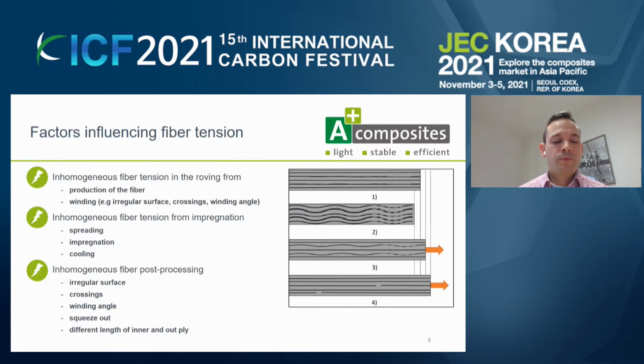So we wonder why there's a big gap between the actual fiber strengths, single fiber strengths or the strengths of the data sheets, and the actual strengths which can be recalculated from the component. And from the literature, it's well known that the influence of the fiber tension is the most important one. So I will split the influence of the fiber tension in three different stages, which goes along the process chain.